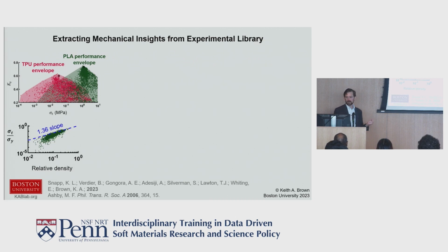But we can compare this to the strength, which seems to change rather gradually, but there is an optimum efficiency. So how do we compare those two ideas? Well, it turns out that there's an optimum density. We want the parts to be low density because if they're low density, the densification strain can be very, very low, which is important for efficient parts. And so there ends up being a maximum of the KS as a function of relative density. That means you want to park right here at about 10% density.